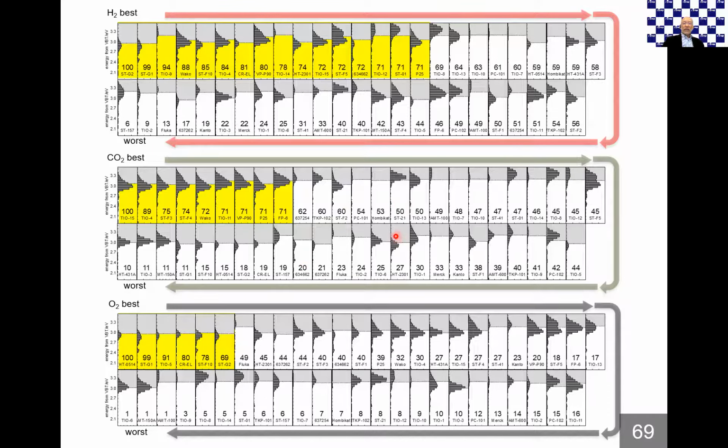For example, one sample shows low activity due to low specific surface area, but the others give low photocatalytic activity because of enhanced recombination with a different structure. But all the higher activity samples give the similar pattern, which means they are almost optimized. That means it is a bit difficult to expect a more active photocatalyst with the conventional preparation method.